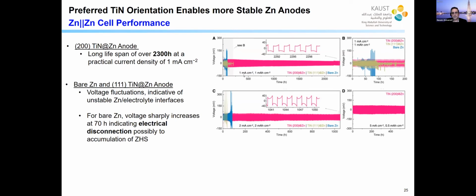This is at a current density of 1 milliamp per centimeter square. In comparison, the two samples with the 111 titanium nitride and the bare zinc, they actually fail. And they fail by increasing the voltage. Given that this is a constant current measurement, this means that there's actually an increase in the resistance, not a short here. So this, we believe, is due to the product formation. This is ZHS, which I will show you in a minute.